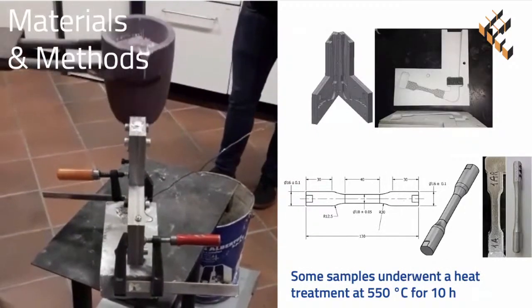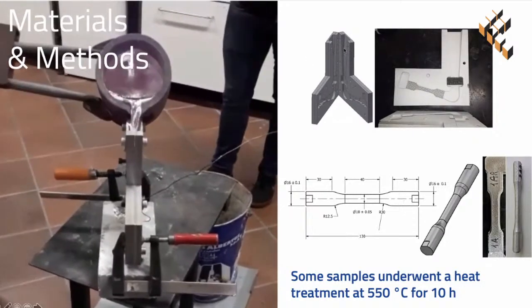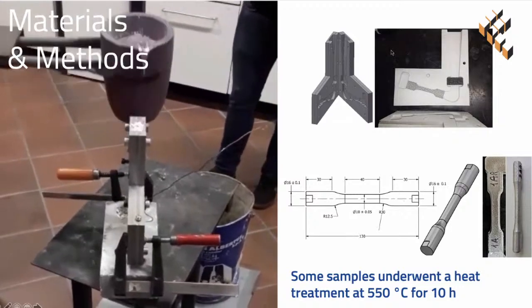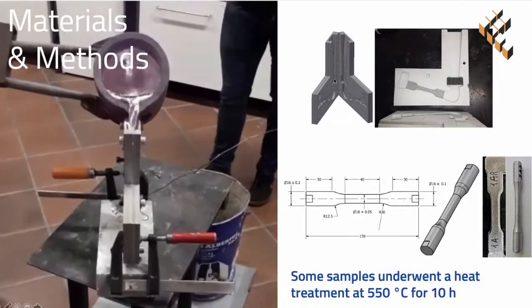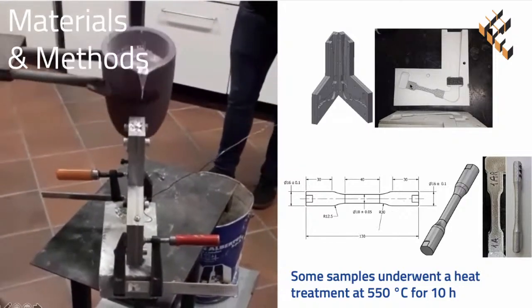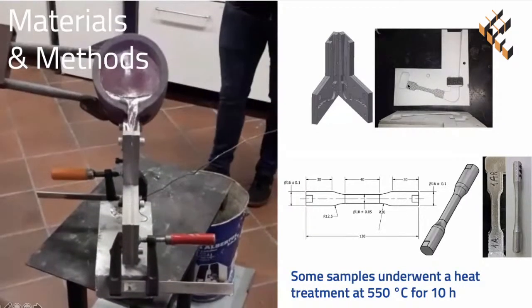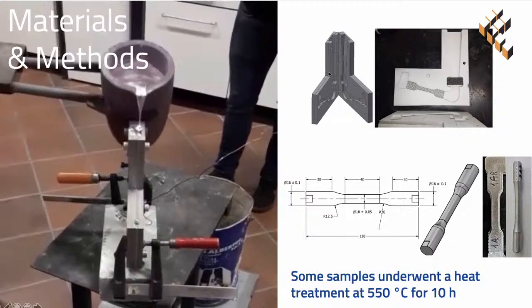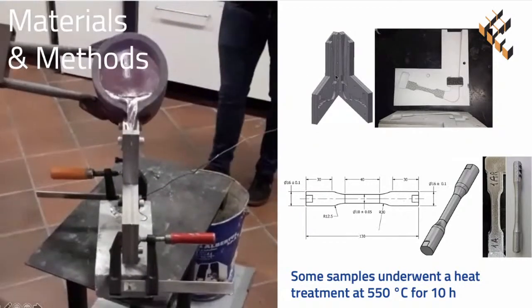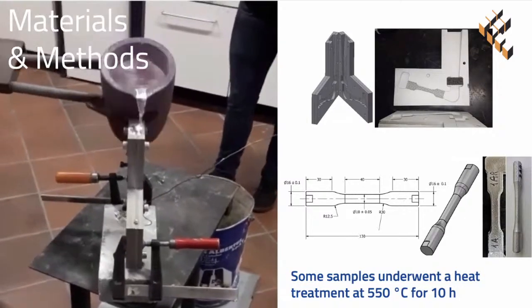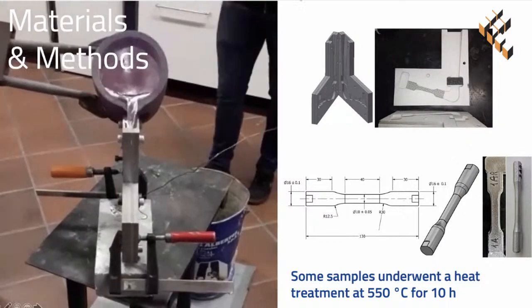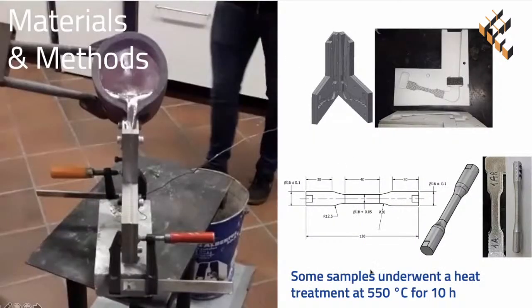So this is the production of the component. We designed a mold. You can see this on the right side of this picture, the mold with the cavity that is the shape of dog bone samples. Inside it, we put the steel wire mesh, and we poured the aluminum alloy inside the cavity with the reinforcement at the inner side. We also investigated the effect of heat treatments carried out at 550 degrees for 10 hours in order to understand if there is some interaction between the materials, the aluminum matrix and the steel, induced by diffusion of elements.